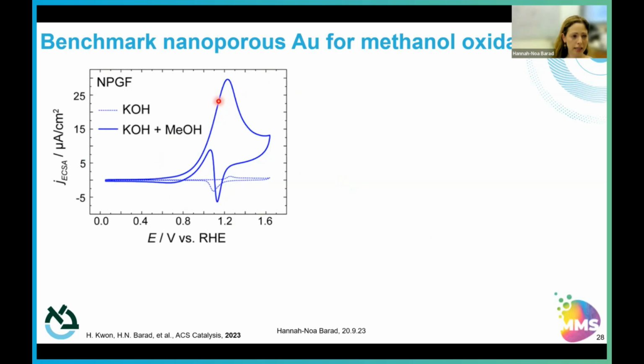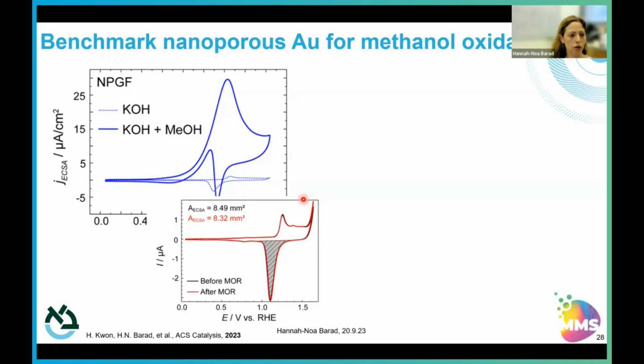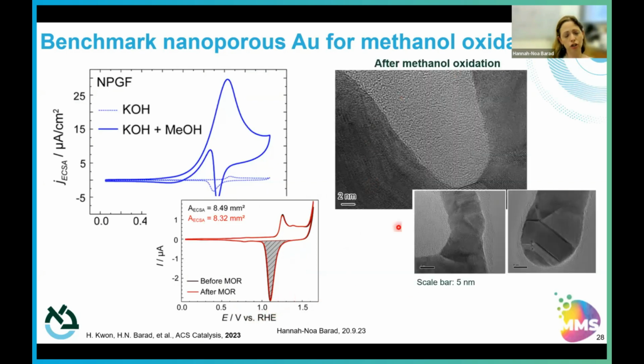And you can see nice activity for it, comparable to, of course, other media that's tested, so other types of gold, and also very low reduction in our electrochemical surface area before and after the methanol oxidation. And if you look into the TEM images of the different ligaments and concave structures, you can see that we still have these very high curvature areas. We still have a lot of different grain boundaries, even though there is some minor surface reconstruction, as we saw before, but it's so minor that it really doesn't even come into obvious light if you look at the TEM.